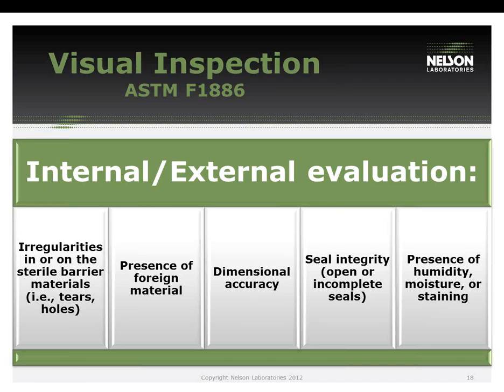Okay, we're going to talk about integrity tests. The easiest integrity test that you can do is visual inspection, and it's regulated by ASTM F1886. And the process identifies looking for irregularities in the sterile barrier system. You're looking for tears, holes, things like that. You're also looking for the presence of foreign material. You can also include dimensional accuracy. If you're running 1/4-inch seals, this is a great opportunity for you to make sure that you're only getting 1/4-inch seals or minimum. Frequently, we've seen samples submitted that the seals have actually shifted to the side, and they're definitely less than the required minimum.